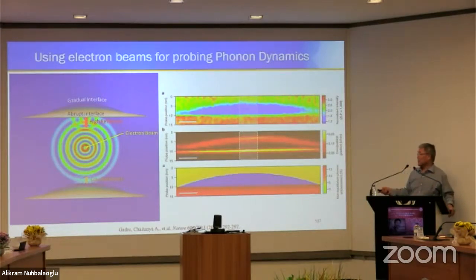We think about the interface effect. We talked to the expert of nano thermal transport, Professor John Chen at Penn State. He's a leader of this nanoscale transport research. And then he built the models to see whether or not we get the result from simulation. It turns out that it worked very well with our intuitive model, and supports the refraction of phonons depending on the sharpness and composition of the interface.